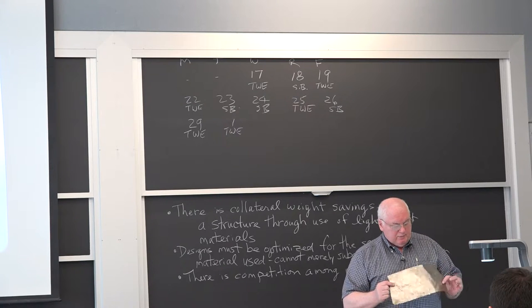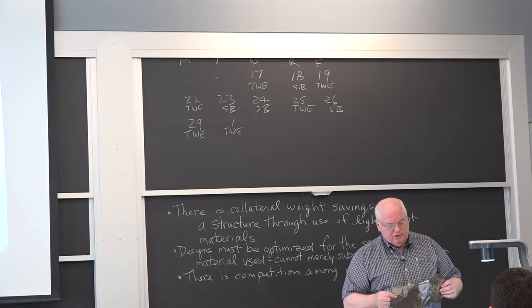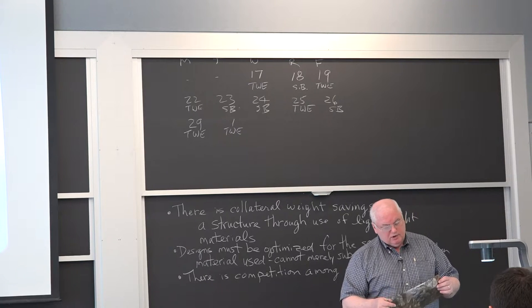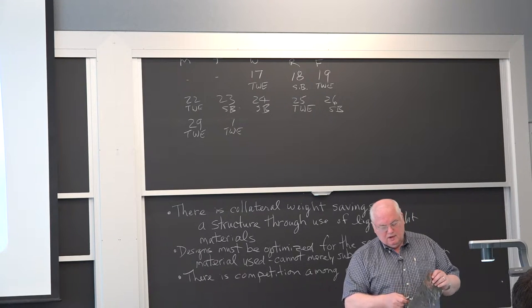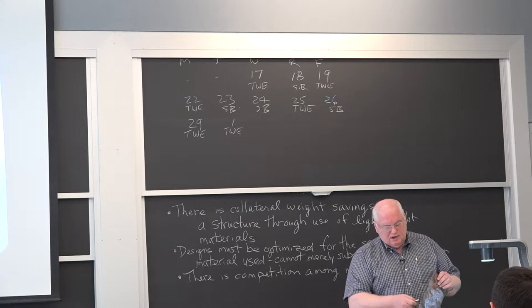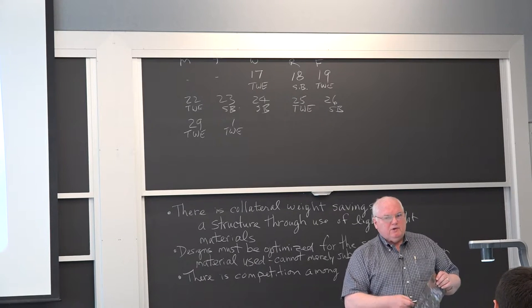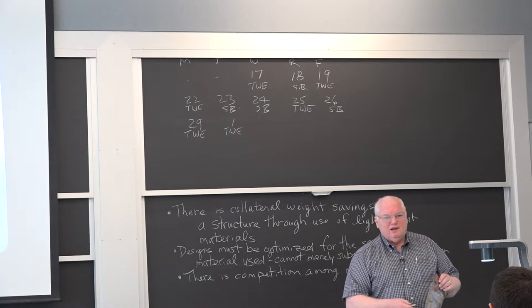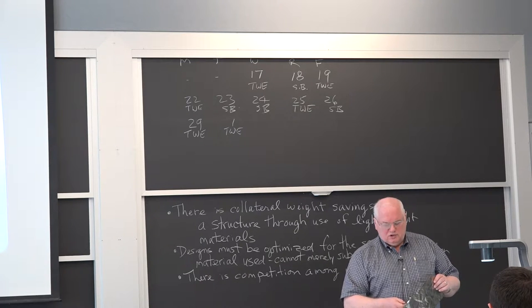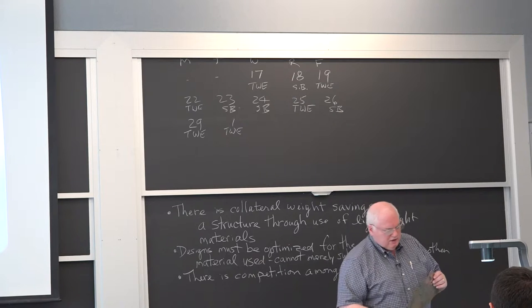That's as thick as they can make it, and it solidifies at about 1 million degrees per second, or 1 million degrees Kelvin per second. And it is the world's softest magnetic material. You can't really tell by doing this, but it has lower magnetic losses than any other material.